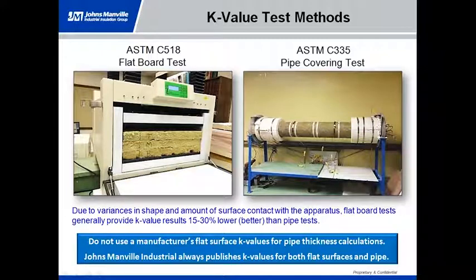Now with the pipe test, if I wanted the same 700 degree mean temperature, my pipe temperature now needs to be 1325 degrees, and then my room temperature at 75 degrees would give me a mean temperature of 700 degrees. So we have a much larger 1250 degree temperature difference. The other thing that we have here is there's radial heat transfer. Okay, so we're measuring heat transfer coming off something round. So imagine you have heat at the pipe, and then as it goes out in this pie wedge-shaped configuration, you have a lot more material to spread that energy over,